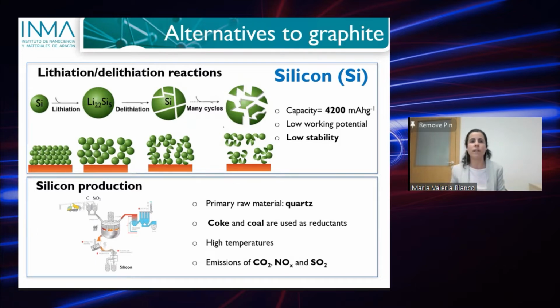And this is because during the lithiation and delithiation of silicon, we have a repetition of expansion and shrinkage of the particles. This causes irreversible structural changes, crack formation, and leads to particle pulverization at the end. It causes really poor cycling stability of the anode and also loss of electrical contacts between the components. Therefore, the cycle life of silicon anodes is really short, and this is the major drawback hindering the commercialization of pure silicon anodes.